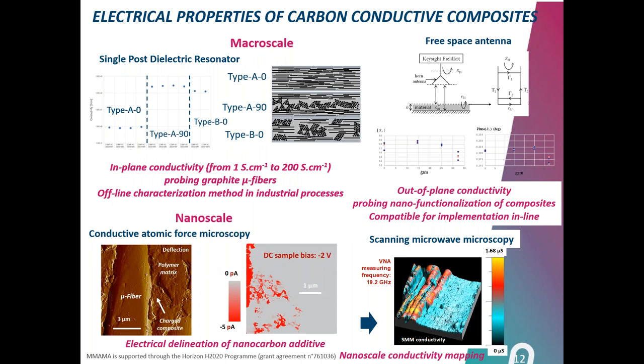So when you have all the fibers aligned in one direction, you get a good conductivity in one direction, but the overall conductivity in the plane is not that great because charges have some problems to move orthogonally to the fibers. However, when you pile up prepregs with different orientation, you end up with something which is much more conductive. And this was possible to observe with the resonator, in this case, the single post, because it's very conductive.